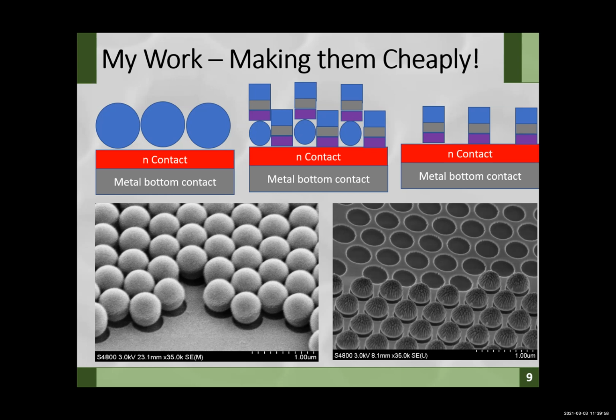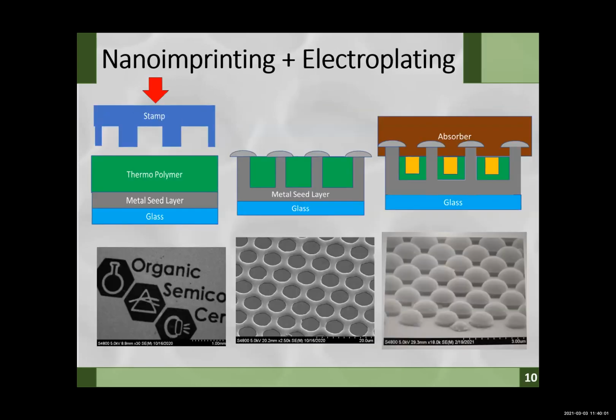And then once we have this structure, you can copy it using a method called nanoimprint lithography. Basically you have a thermopolymer and you've made a stamp using the nanospheres, and then you stamp it into your polymer, and then you can reproduce the structures, and you get the exact things which you need.